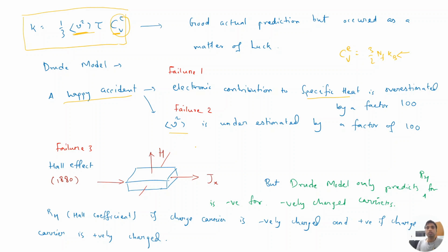And another important failure of the Drude model is the Hall coefficient. You need not know exactly what it means right now, but keep in mind that R_H is negative if the charge carrier is negative, for example electrons, and the Hall coefficient is positive if the charge carrier is positive, for example the holes of a semiconductor. The Drude model only predicts that R_H is negative, for negatively charged carriers. It does not say why R_H can be positive, and it has a very big numerical mismatch also. We do not get the exact value of the Hall coefficient from the Drude-Lorentz model. That's all you can remember for now.